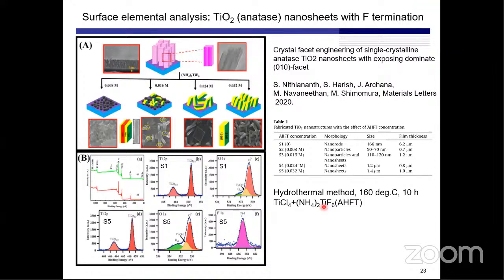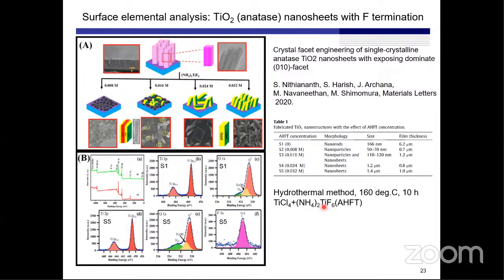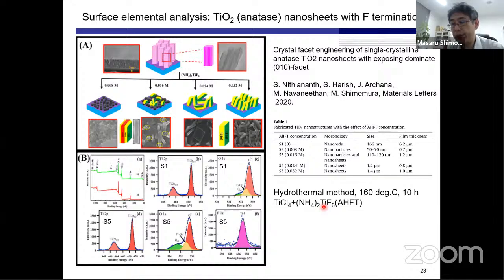One reason is the sensitivity factor of X-ray. The sensitivity factor of light elements like boron is very low compared with transition metals or very heavy elements. In comparison with the background deviation, if the background is high, then the deviation is also high. If the peak is very small, it is buried in the background deviation. That is the main reason you cannot obtain the impurity peak.